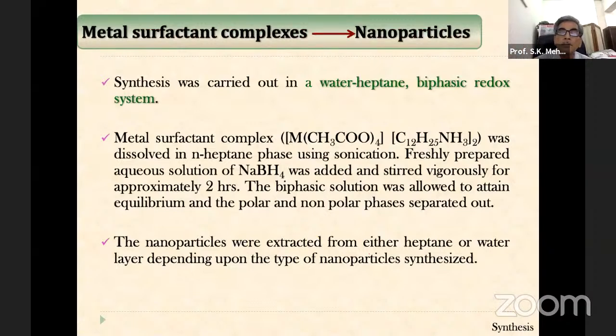I'll briefly tell, for our students, the basic idea. So synthesis was carried out in a water-heptane biphasic redox system, a very simple process. We took the metal acetate and dodecylamine, and dissolved them in the N-heptane phase using sonication, and then you use sodium borohydride, and slowly you can add it over 2 hours, and then you allow this biphasic solution to reach equilibrium, and the polar and non-polar phases separate.